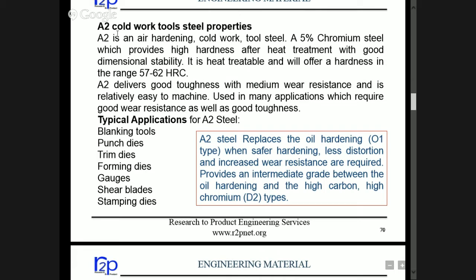Now A2 is the air hardening. So A2 cold work tool steel, right, is an air hardening cold work tool steel, around 5% chromium steel, which provides high hardness after heat treatment with good dimensional stability. It is heat treatable and will offer a hardness in the range 57 to 62 HRC. So toughness is good, and A2 steel replaces the oil hardening O1 type when safer hardening, less distortion, and increased wear resistance are required. So it's a little more expensive than O1 because the properties we get and the tool life we get is more than O1.